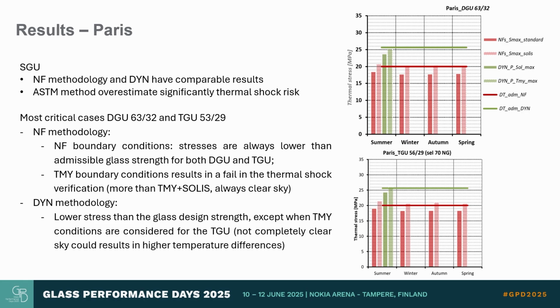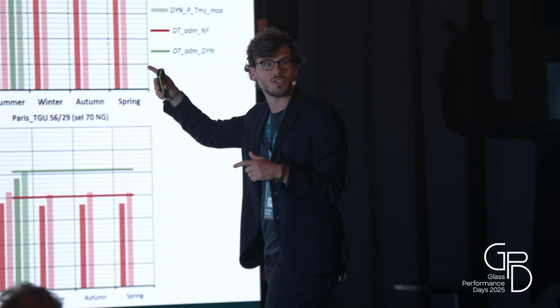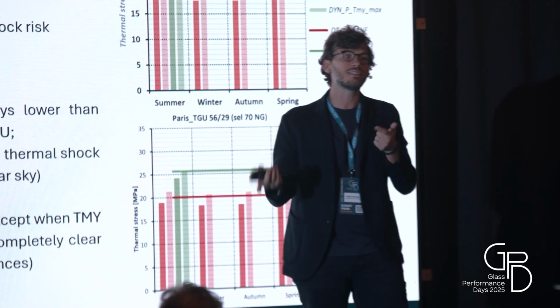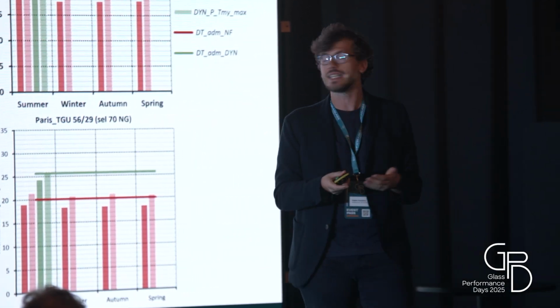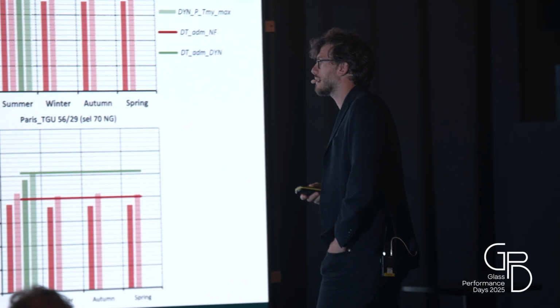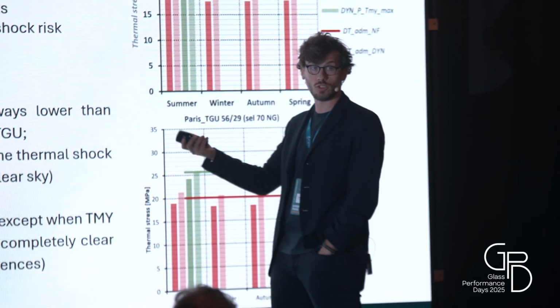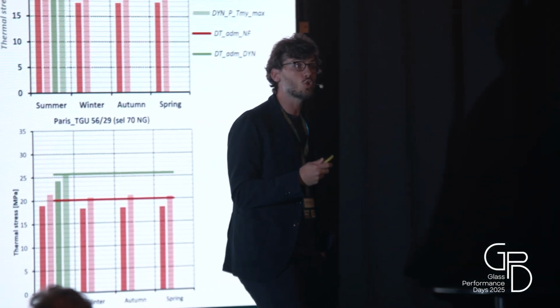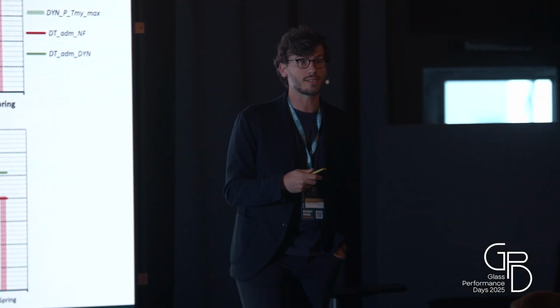and that's with real sky more than what would happen instead with a simple clear sky. And that's because mainly in a real sky I have the effect of the albedo of the clouds that are increasing the peak of solar radiation, and that in terms of delta T would cause an effect that is increasing thermal shock risk assessment. With the dynamic methodology, we are able to quantify with a better accuracy the stresses, and